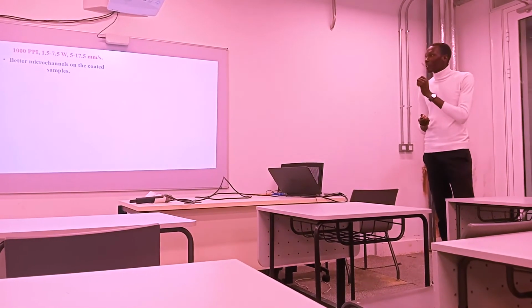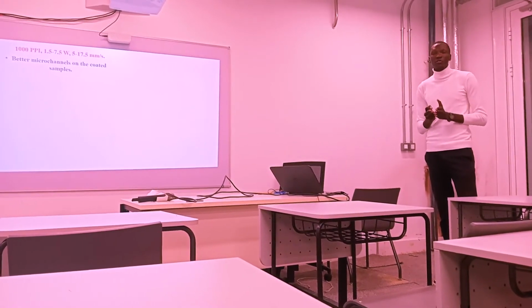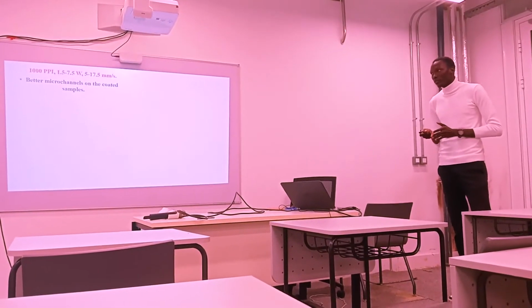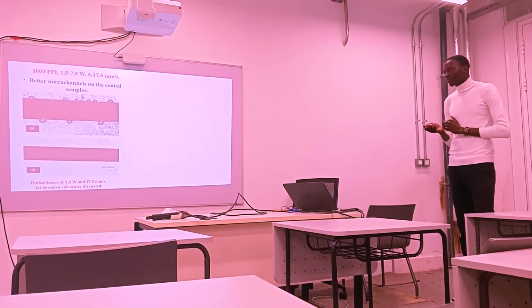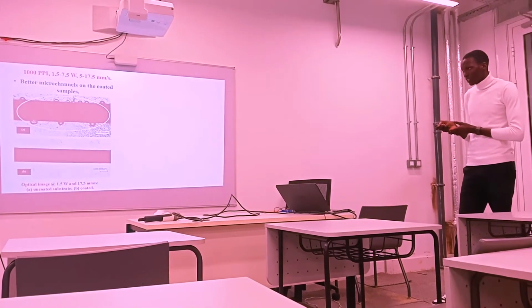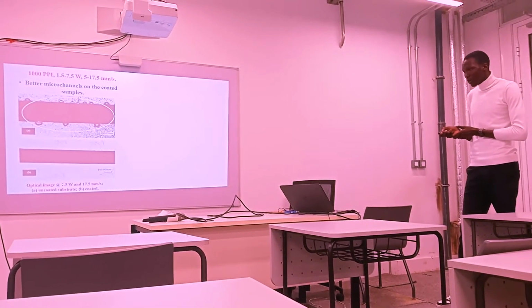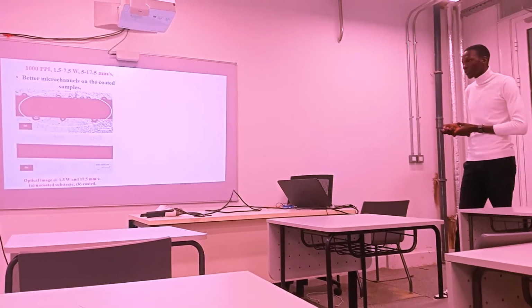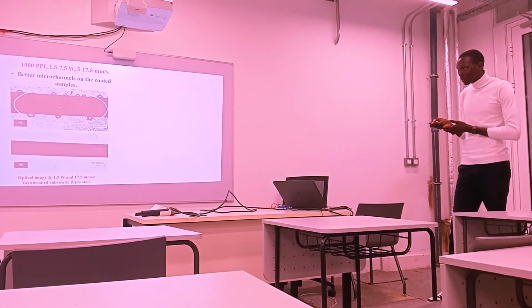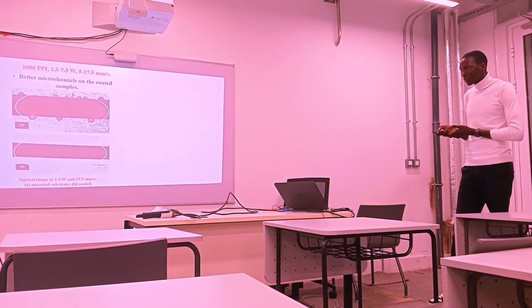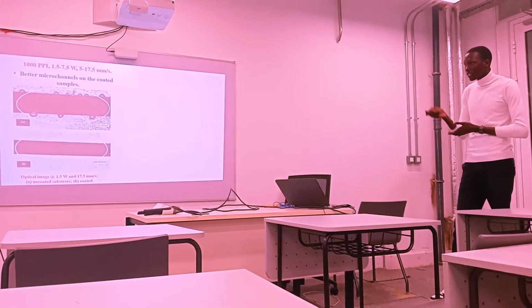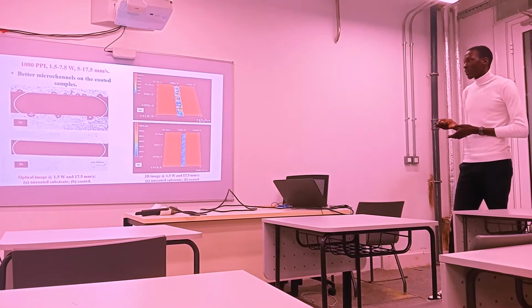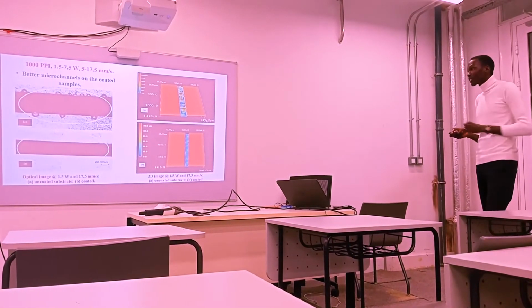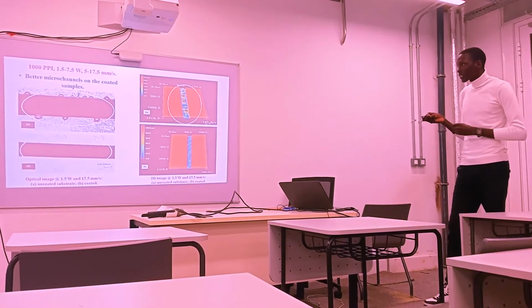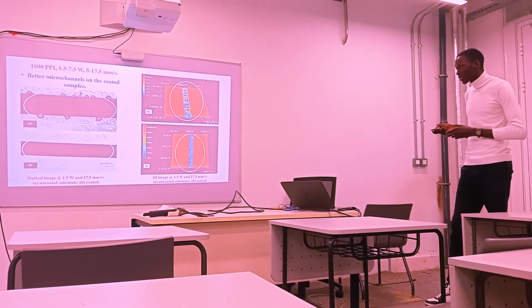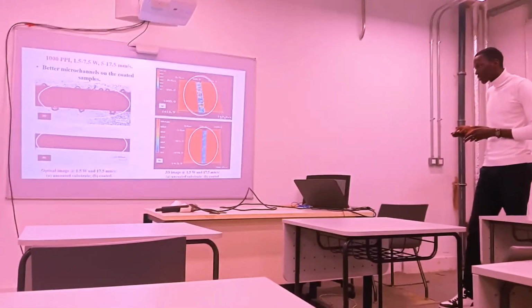Now, we got better microchannels on the coated samples compared to the channels on the uncoated samples, as we can see here. This is what we got at 1.5 watts and 17.5 millimeters per second. This is uncoated, this one. Then this is when we coated with aluminum. We got better microchannels. Then this is a 3D image for the uncoated and then for the coated, under the same condition.